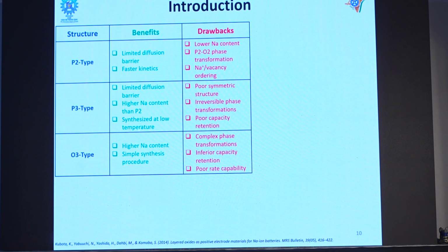And P3 type materials are also very good, similar to P2 type, but they suffer from irreversible phase transformations. I said crystal structure is very important. If it undergoes a crystal structure transformation which is not reversible, then it will suffer from a permanent capacity loss in the system. Capacity means the amount of charge the material can store per unit mass. So the specific capacity will be lost and the material will decay slowly. And these P2 type materials have lower sodium content, but P3 type materials have poor capacity retention.